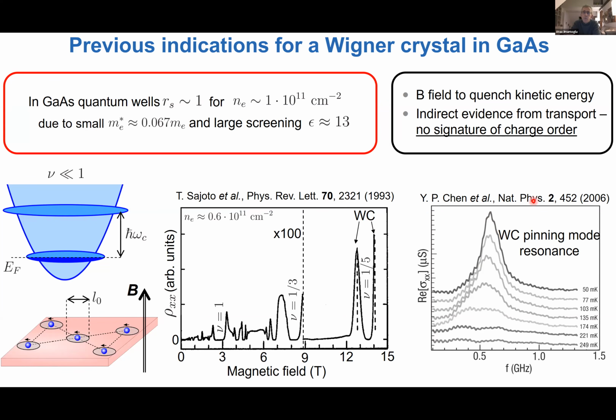Now, more convincing experimental evidence was the verification of a prediction that the Wigner crystal that is pinned by the weak disorder can be unpinned, resulting in a substantial increase in conductivity if one hits the system with an AC drive with characteristic frequencies on the order of gigahertz. And indeed, here is a result from 2006, which showed that at low temperatures, the conductivity can indeed increase. Now, what I would like to emphasize here is that these are all indirect measurements, in the sense that they're consistent with the presence or emergence of charge order, but they do not tell us directly of the existence of charge order.